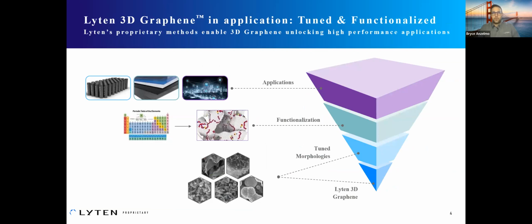So maybe look at it a bit of a different way. We don't just take the material and throw it over the fence, but we really take the 3D graphene construct and tune that morphology, so modify and manipulate the 3D structure. But we also can add chemistry or functionalization, however we like to look at that. Functionalization really captures not only the surface chemistry, but the ability to, let's say, maybe have a coupling agent if that's needed for that end polymer system. And then that's where it goes into the application, as I mentioned. Composite, sensor, and battery is largely what we're focused on at the moment.